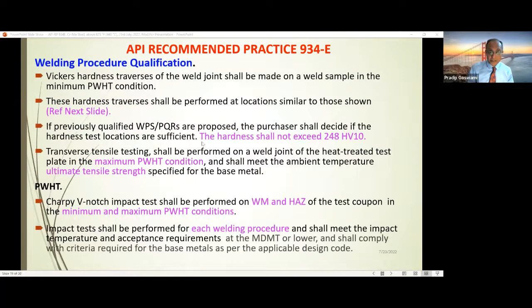And what is to be followed after the welding? Conventionally, as you know, following the post-weld heat treatment, your tensile and bends are very common. In addition, the hardness has to be met. Hardness shall not exceed 248 Vickers. And transverse tensile shall be performed on weld joints in the heat-treated plate in the maximum post-weld heat treatment condition. The maximum post-weld heat treatment condition, as I specified,